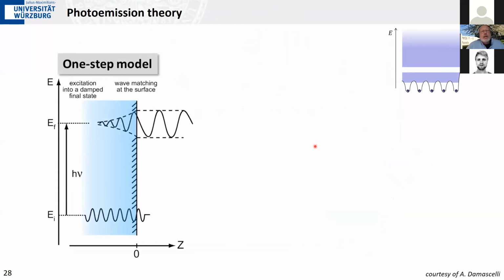And in the most simple picture, we can think of this as a situation where we start out with a half-infinite solid with a surface. The surface is here at z = 0. This is our solid, and this is an energy axis. And here we have electrons sitting in some core level states or some Bloch states in our solid. We have to excite them in energy to a state that lies well above the vacuum level. And then the electrons can come out of our solid. They have to penetrate the surface, and then in the vacuum they will propagate as free electron waves until they finally hit our detector, where they get analyzed in energy and finally create a signal that we can count.